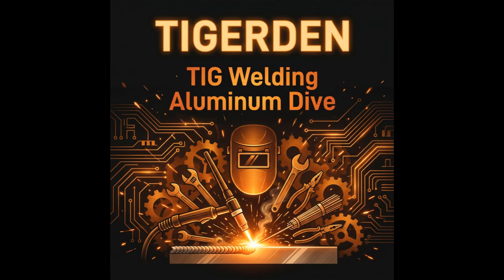It really is, and you can see it happening. If you look closely at the edges of a good aluminum weld, you'll see this frosty etched zone. That's the area where the AC arc has literally scrubbed the surface clean. If you don't see that frosting, you aren't getting cleaning action, and your weld is probably going to fail.